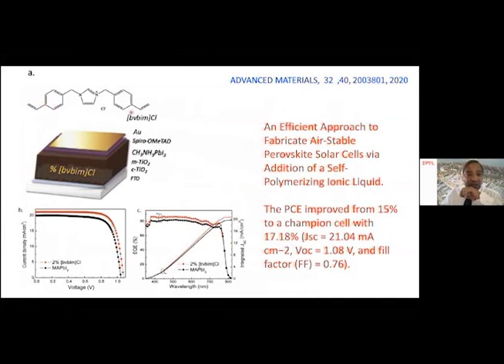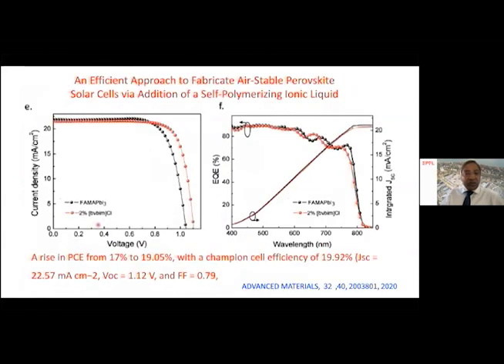So this is another ionic liquid where we have two double bonds on the top. Using methyl ammonium as a standard perovskite composition, we increased the efficiency from 15 to 17%. However, by changing the perovskite composition to formamidinium and methyl ammonium as shown here, the reference sample gives us 17%, and with 2% of this ionic liquid gives close to 20% efficiency of the perovskite solar cell.